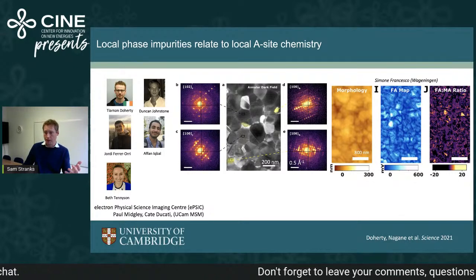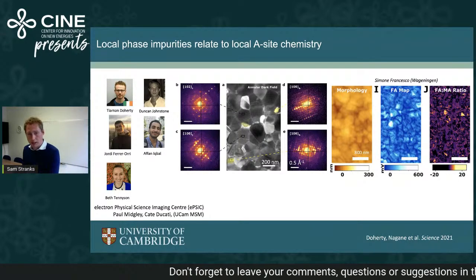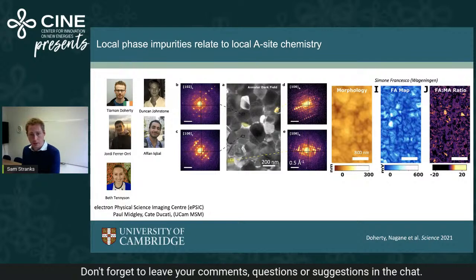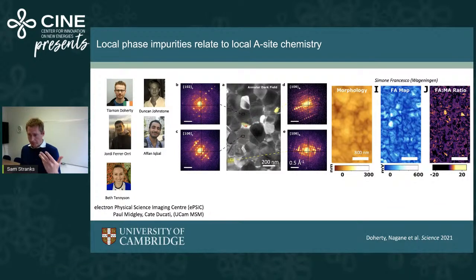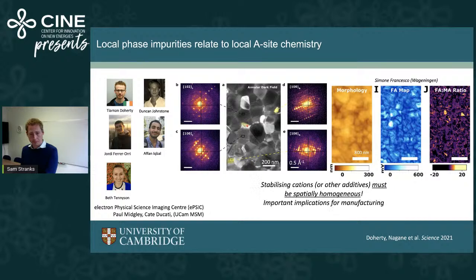And so these are more cubic and they transition much more readily back to these hexagonal polytypes, which causes these polytypes to be there. What that's saying is that these stabilizing cations, these alloys, must be homogeneous to induce tilt everywhere to avoid these hexagonal phases, even these tiny hexagonal phases, from forming. That will have quite important implications for manufacturing of these cells and how much tolerance we have for chemical variation, for example.